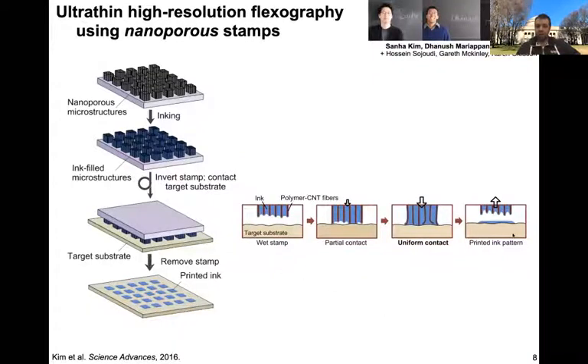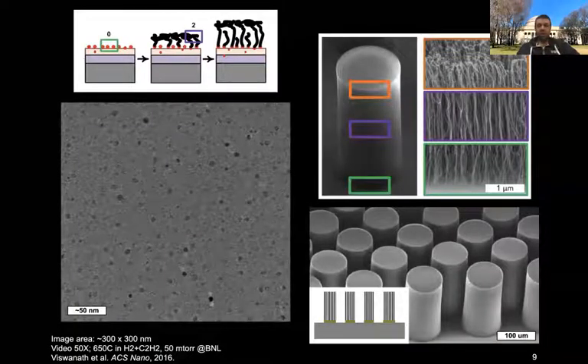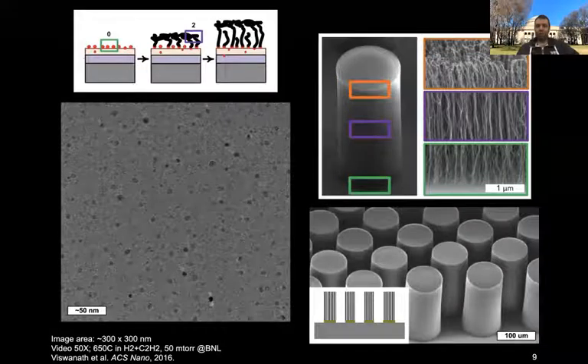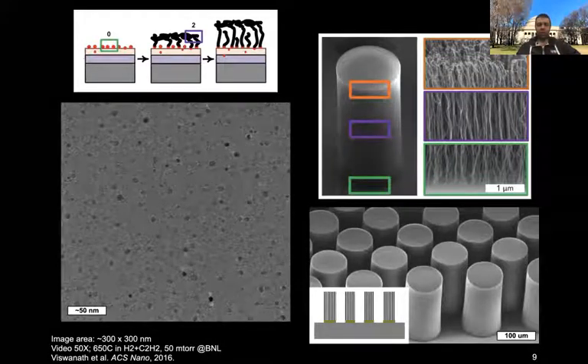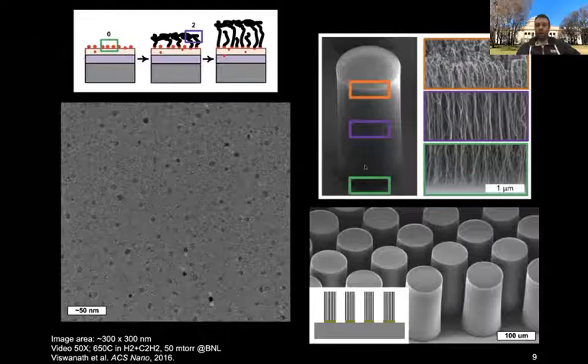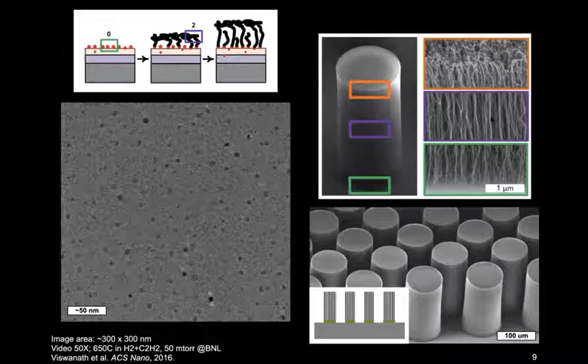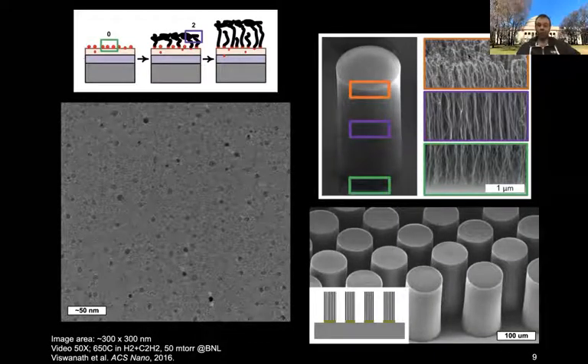Whoops. I'm sorry, I advanced too quickly. It is effective in enabling us to print very, very thin layers of ink. And the synthesis of CNTs in the form of these vertically aligned forests and vertically aligned microstructures is a topic of our great interest for many years, since I was a graduate student back at MIT, and we have understood how to control this well enough, at least, such that the CNT forest microstructures can be of uniform height and have a controlled architecture. And what I will show to you is it's really the architecture and mechanical properties of the forest and of the feature of each stamp that make this process possible, not only the bulk mechanics, but also the surface mechanics where the stamp contacts the substrate and where the ink is transferred. And we've also enabled this work by many studies of the CNT growth process.